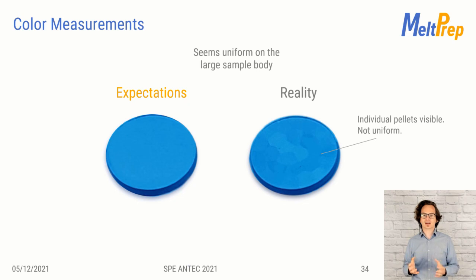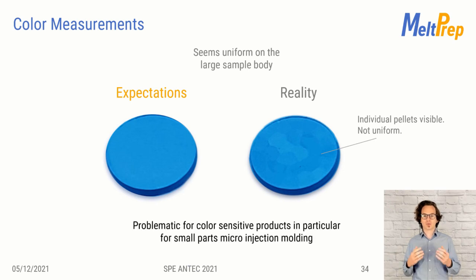But if we take a closer look at the VCM sample, where we can basically maintain the pellet shape, as we saw in the mixing example on one of the previous slides, we see that the pellets are not uniform. They have different color. This is a problem when you want to produce color-sensitive products, or in particular when you desire small parts via microinjection molding, for example.